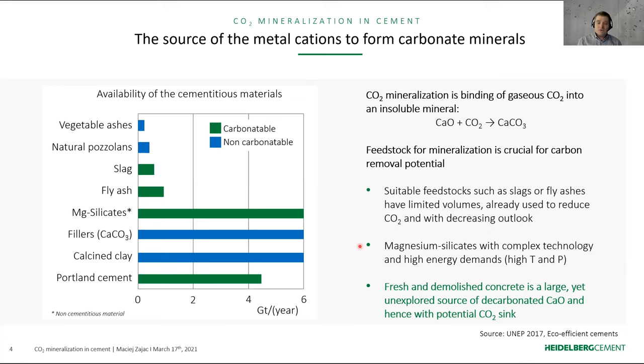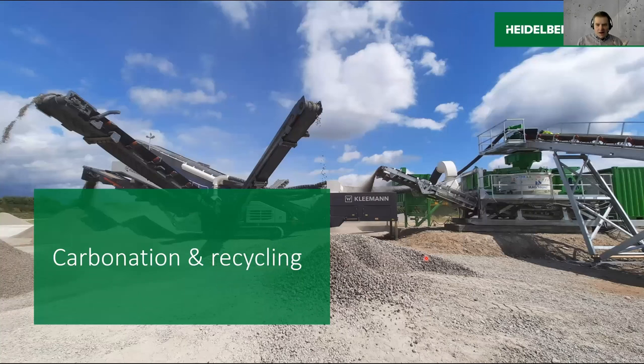So what we find out is that fresh and demolished concrete is a large source of reactive CaO that can be used for mineralization. And then within the next slides, I would like to share my experience with carbonation of demolition concrete, using demolition concrete as a sink for mineral carbonation. In other words, we're going to speak about the carbonation and recycling process in the cement and concrete industry.